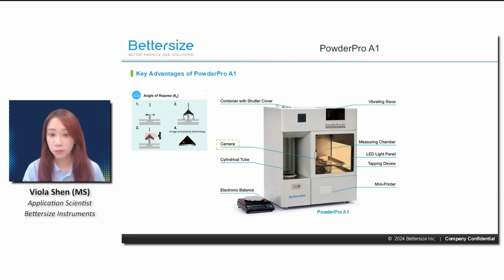The Powder Pro A1 provides a highly compact and efficient solution with several notable advantages. This instrument is equipped with a high-definition charge coupled device, the CCD camera, that captures clear images of the powder pile. This allows for the precise measurement of critical flowability parameters such as angle of repose, angle of spatula. And thanks to the advanced image processing technology, these measurements are not only accurate but also highly repeatable.